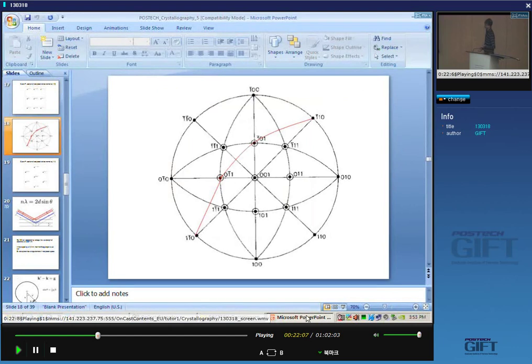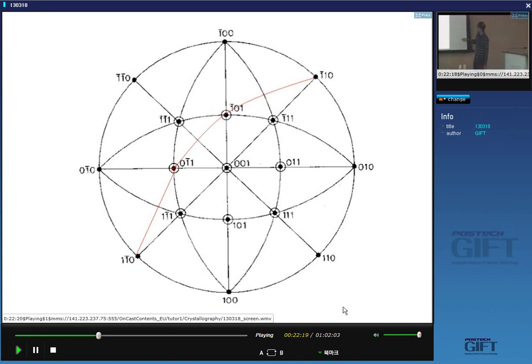Okay, now we plot the 1 1 1 reciprocal lattice section. So I identify the great circle, which is at 90 degrees to 1 1 1. So all of these points here lie at 90 degrees to 1 1 1. You can check that by taking a dot product between any of those, and you will see that you get a zero. So, for example, 1 1 1 dotted with 0 bar 1 1 is obviously zero, because 1 times 0 is 0, 1 times -1 is -1, and 1 times 1 is 1, therefore is zero.